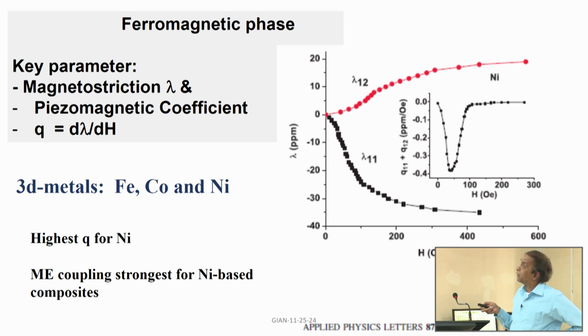So, for the ferromagnetic phase, the important parameters are magnetostriction and the piezomagnetic coefficient. For 3D metals, iron, cobalt, and nickel, among the three, nickel has the highest magnetostriction and also the piezomagnetic coefficient. What is shown here is the magnetostriction in parts per million, that is 10 to the power minus 6, versus the bias magnetic field. Lambda 11 is the magnetostriction measured parallel to the field, lambda 12 is perpendicular to the field.